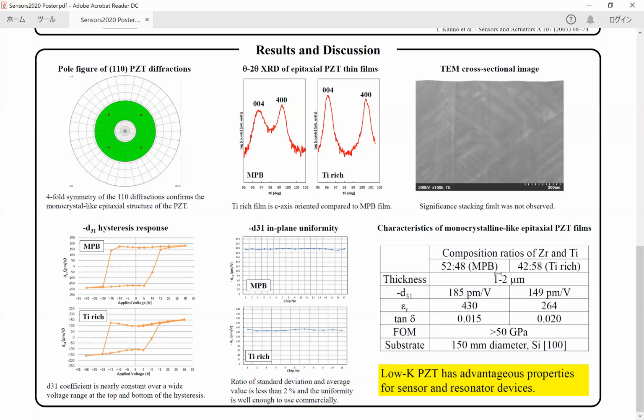MPB and titanium-rich PZT films have average piezoelectric D31 coefficients of 185 picometer per volt and 149 picometer per volt, and relative dielectric permittivity of 430 and 264, and dielectric loss of 0.015 and 0.020, respectively. Both figures of merit derived from the D31 and the permittivity are over 50 gigapascal.